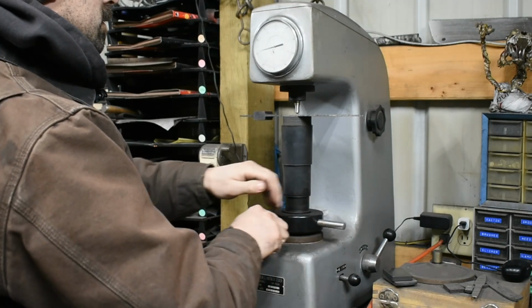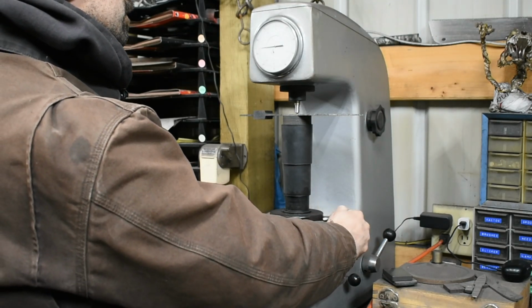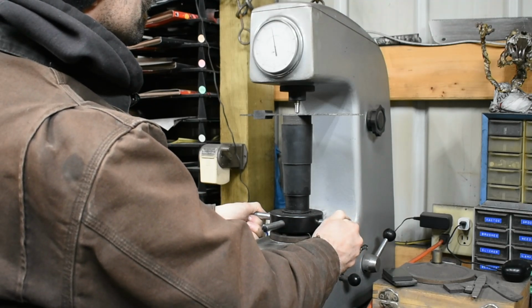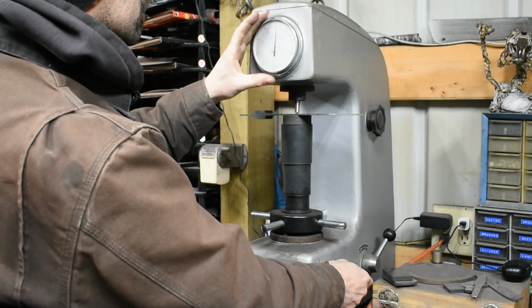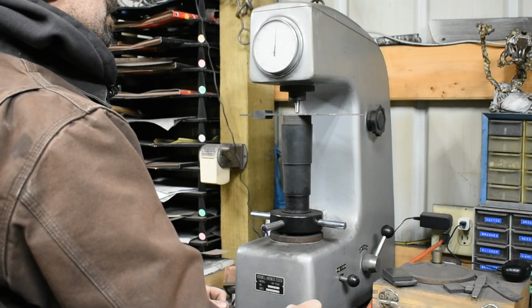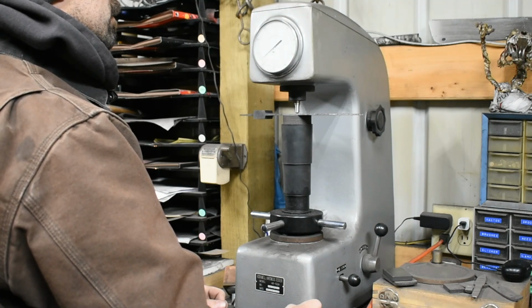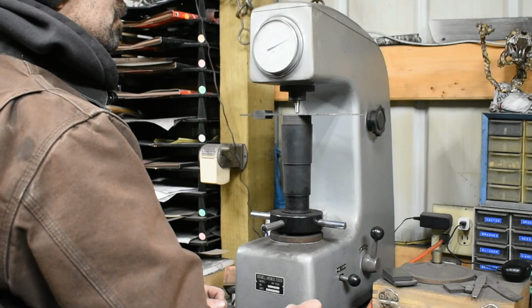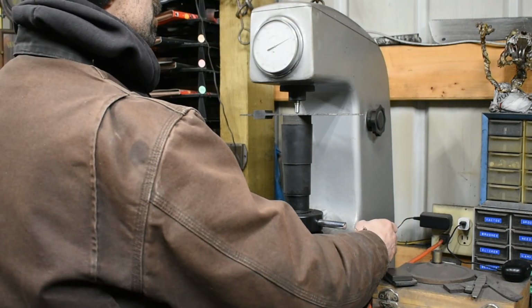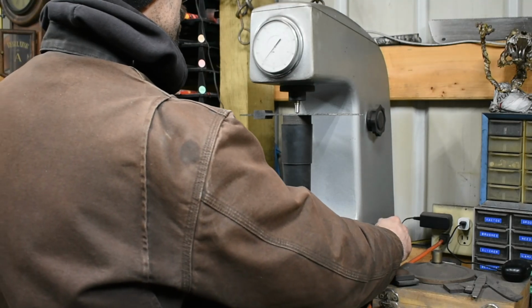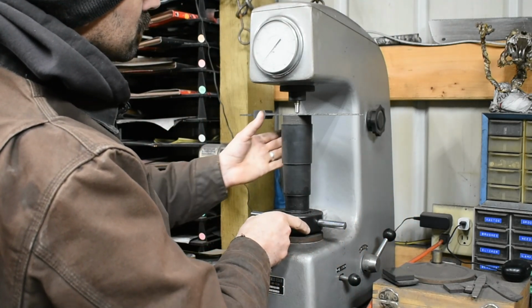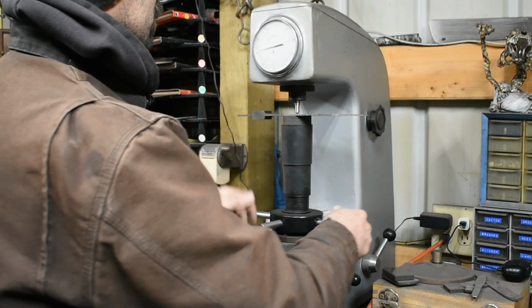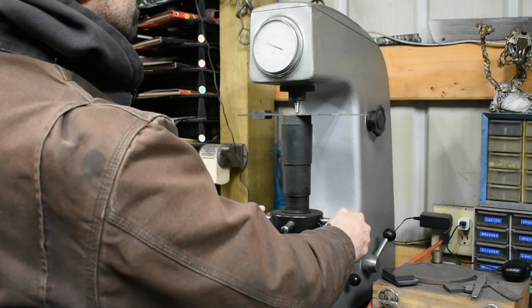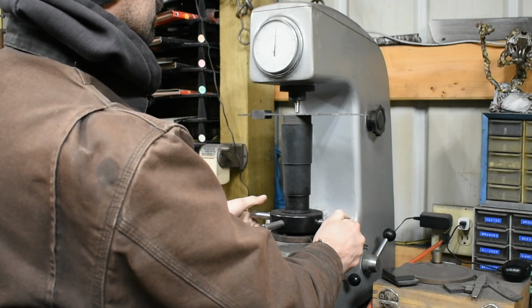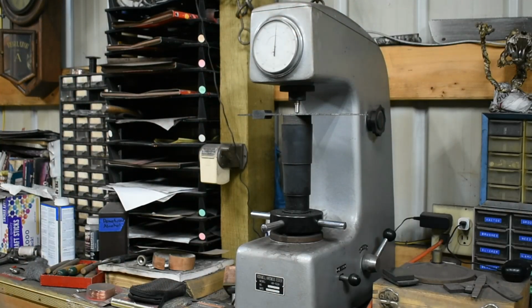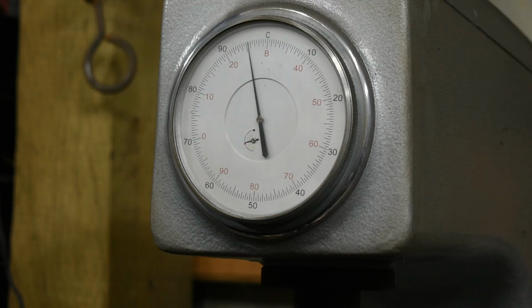So here we are testing a blade. It always takes a couple of tests to eliminate outliers from things in the machine adjusting to the new thickness. So you take 5, maybe 6 tests and average the results out over slightly different areas of the blade. We've got our initial load, secondary load, and now we're seeing what the difference between the two is. The first one's like a 61 Rockwell, which was a little low as I expected. Usually the first test will be a little low. It's rare to have an inaccurate test be a too high reading.